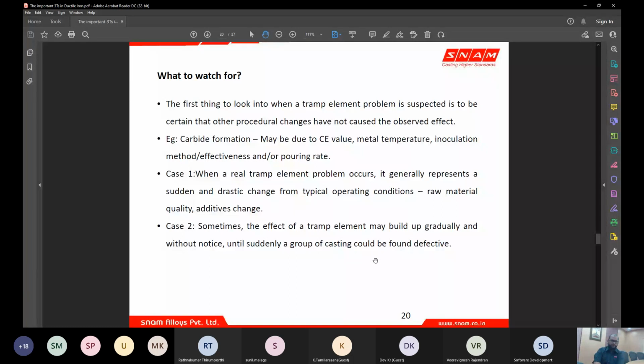So there can be case two, where some elements can build up by themselves. It is in a very small amount. Say for example, titanium. Titanium comes from the liquid metal, and say our pig iron has some titanium, or steel scrap has some titanium. So we keep using our titanium-bearing pig iron and scrap, and our returns will also contain some titanium. When you keep adding, some trace elements keep building up, because there is very little loss available for those trace elements. This keeps increasing, and over a period suddenly you will end up with a very high level of trace element, and very high rejections continuously coming up. This could be because of continuous buildup.